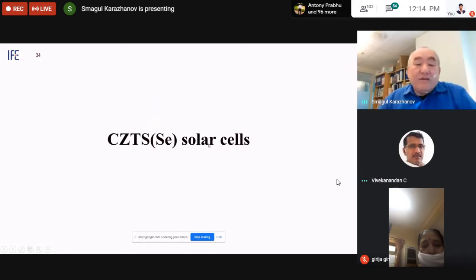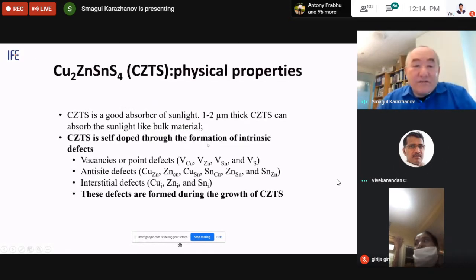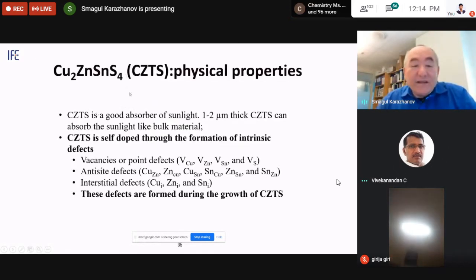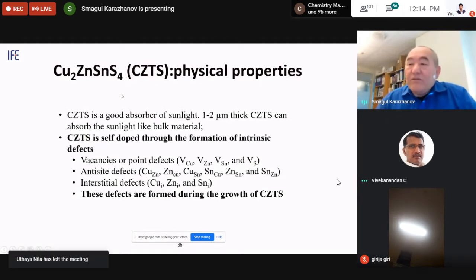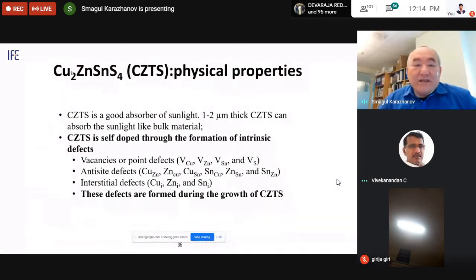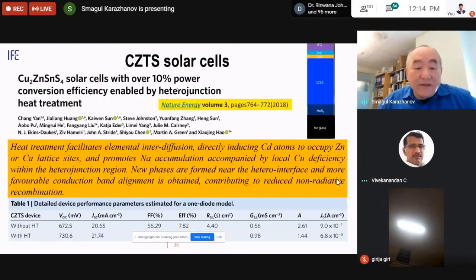Yes. Now let's come back to CZTS solar cells, copper zinc tin sulfide. So in about 2013, this was a very popular type of solar cell. In cadmium telluride, CIGS, and CZTS, electrical conductivity can be controlled by controlling cation vacancies. So this is an advantage of these cells compared to silicon ones. We don't need intentional doping to control p-type conductivity.